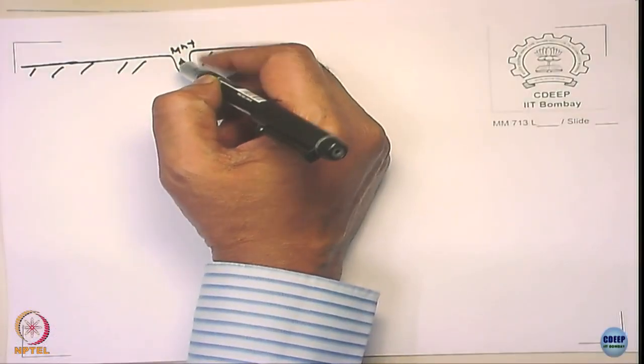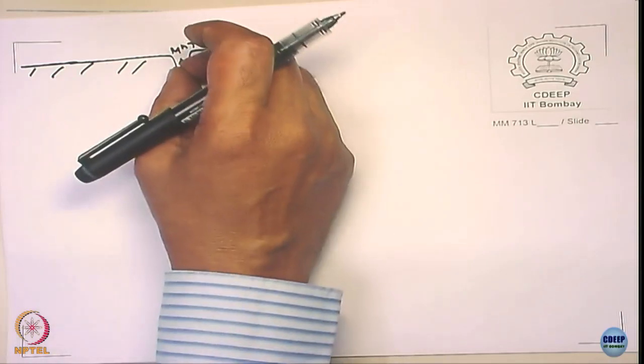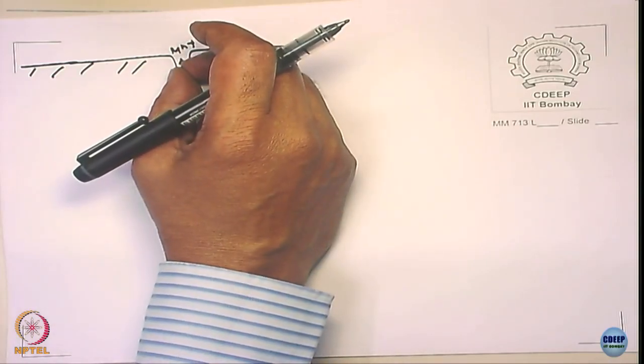No, what do the metal ions first of all do? If they stay here, what do they do? They form hydrogen ions, right? They hydrolyze. If these ions are quickly moving away from the surface, what will happen to acid formation? The acid formation reduces, the chloride ion migration also reduces, and so the pit becomes unstable, okay.